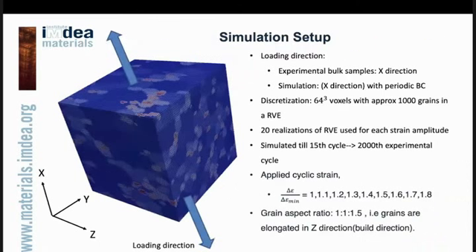Next is the simulation setup, where again we use the RVE. We load in the X direction with different strains, which are normalized due to confidentiality. Twenty realizations of each RVE have been simulated, and we use a trick that each 15th numerical cycle corresponds to 2000 experimental cycles, so that we can easily jump to the higher experimental cycles.